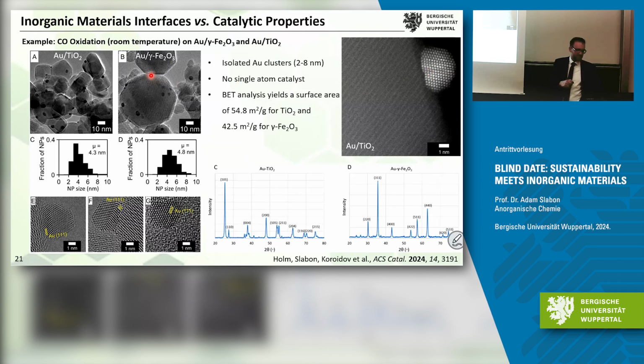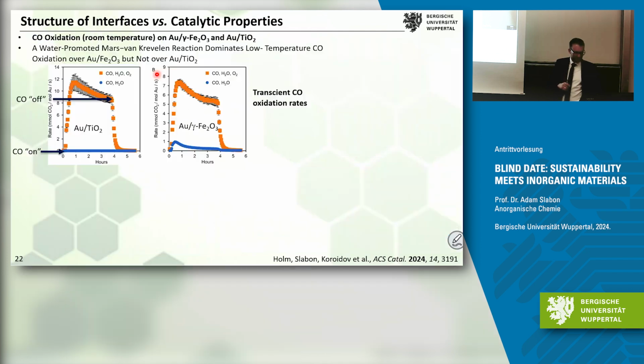Does the interface play a role here? So we tested this in a flow reactor, and it was quite surprising. This is a curve showing the rate of CO2 production as a function of time. At this point we kick in the CO, so it's CO on with water together.